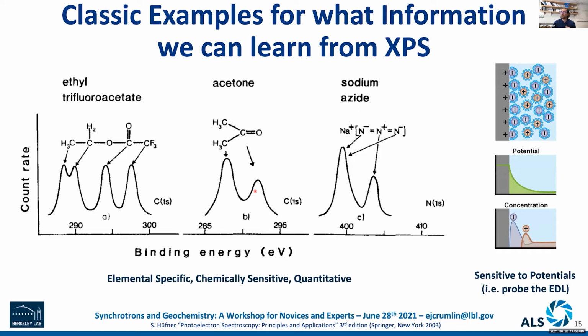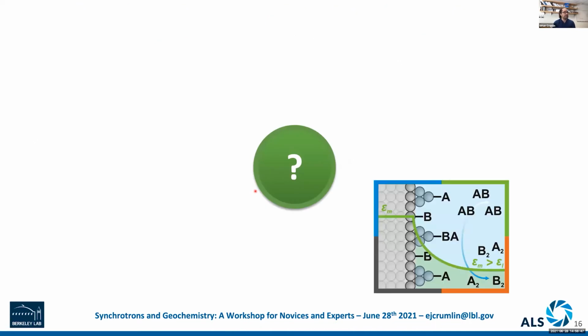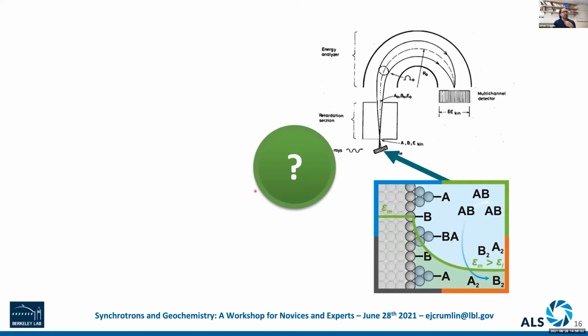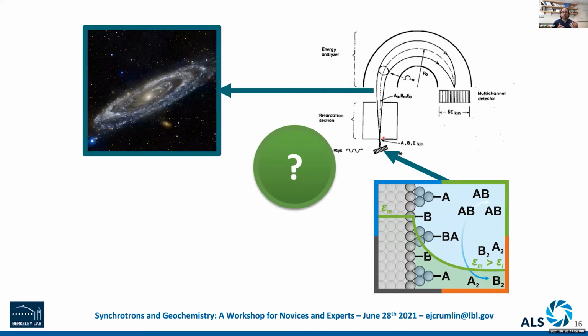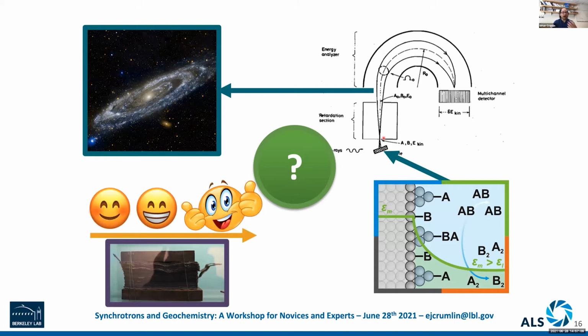And so this is probably one of the most underutilized aspects of this technique, but we'll talk about it briefly as well. So the main challenge is, how do you actually do a technique where you want to look at a real interface? But the technique is looking at the photoelectron, and the environment of XPS is typically a vacuum environment that's lower than space. So ultra high vacuum is traditionally the operating regime. But if we want to look at these real systems while these conditions are operating, to understand how they work, what their function is, how do we make them better, we have to adapt the technique and modify it. So how do we do that?